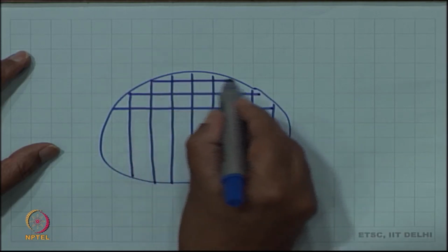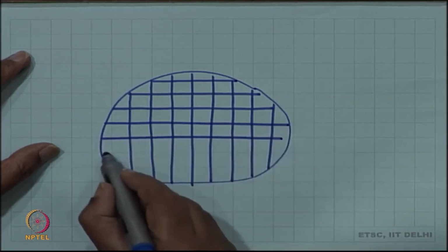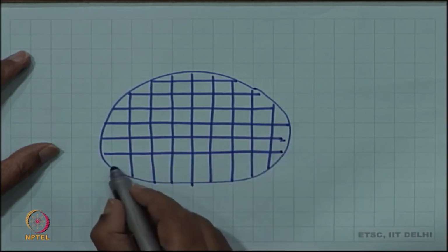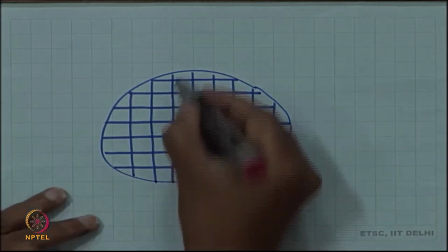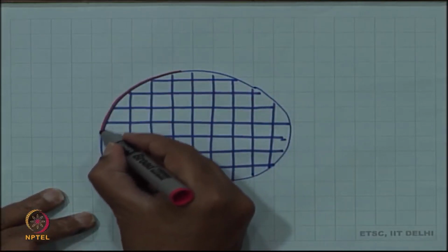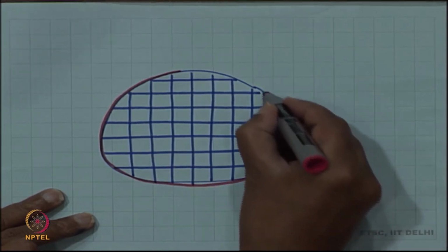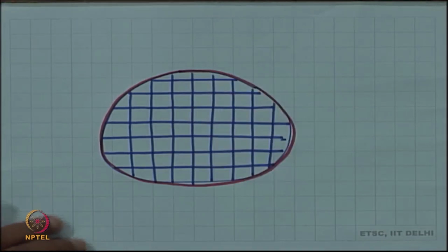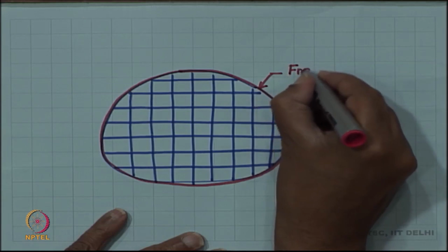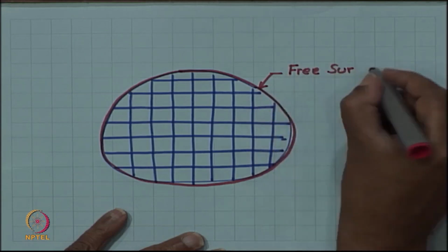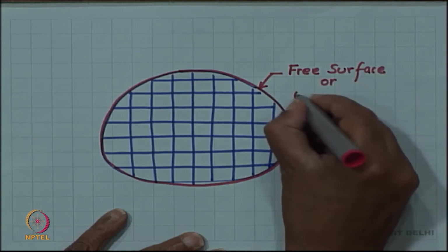But for the moment, if we say it is free of vacancies and it is free of dislocations, still since it cannot be infinite, there will obviously be an external boundary of the crystal, and that external boundary itself breaks the lattice periodicity at that position. So, this free surface is a defect. So, this is a free surface or external surface.